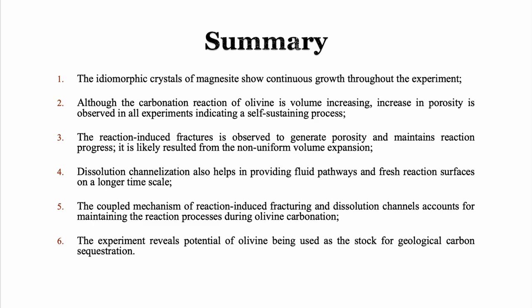So, in summary, we have observed the idiomorphic crystals of magnesite continuously growing on the surface of the olivine. Although the reaction is volume increasing, we also observed an increase in the porosity, indicating it is a self-sustaining process. The reaction-induced fracture is observed to generate porosity and maintain the fluid and the reaction progress. It likely results from the non-uniform volume expansion, which leads to the generation of tensile stress. The dissolution channels also help in providing the fluid pathway and fresh reaction surface on a longer time scale. This whole porosity generation process is a coupled mechanism of both reaction-induced fracture and dissolution channels. And we think that this experiment reveals the potential of olivine being used as a stock for the geological carbon sequestration.